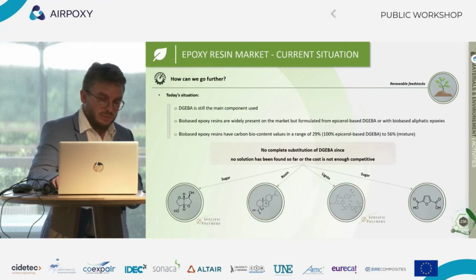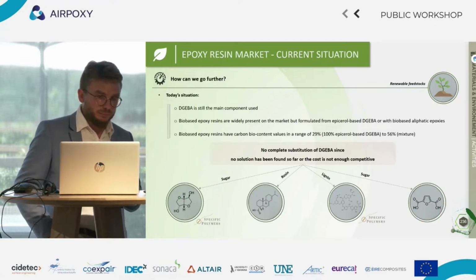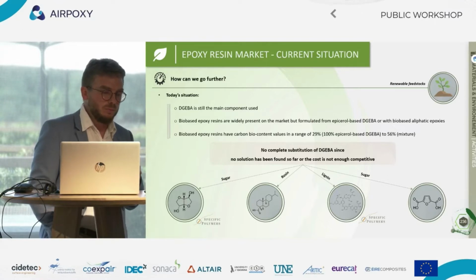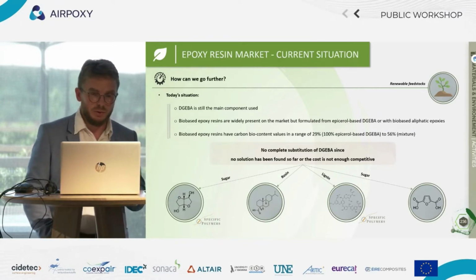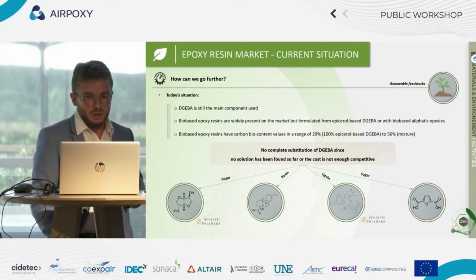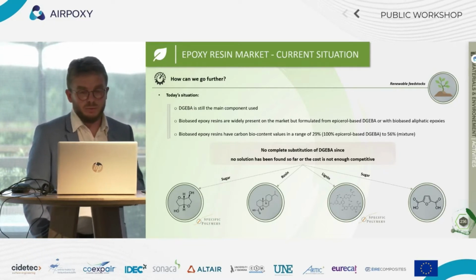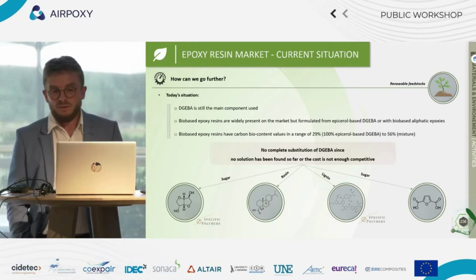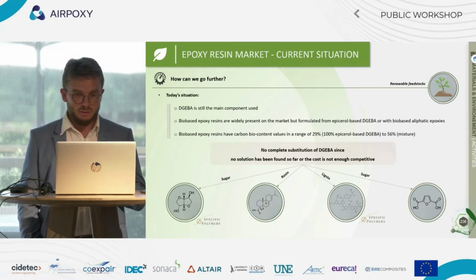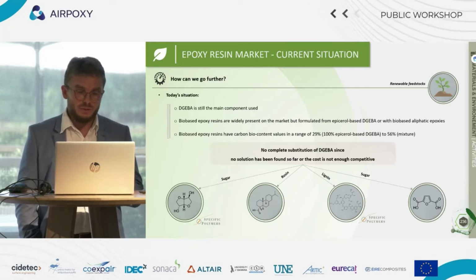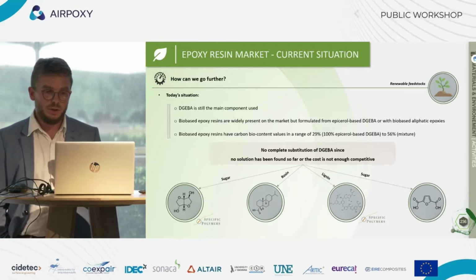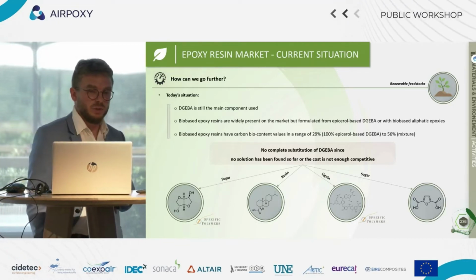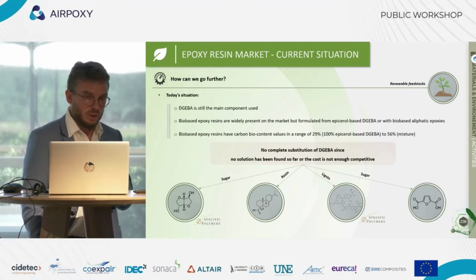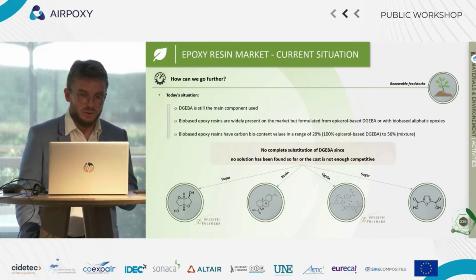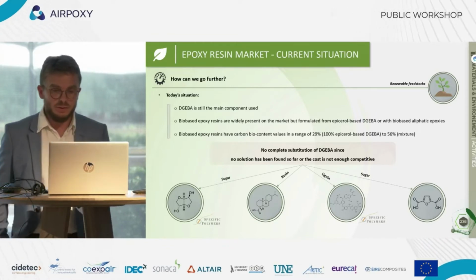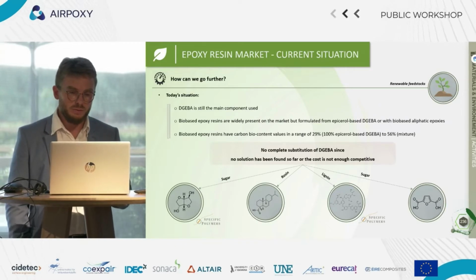So this gives somehow the point where we start, what we want to do. So the problem is DGEBA is still the main component, and we need to find an alternative. Okay, it can be bio-based, but for the moment it's mainly based on Epicerol, and even if it's bio-based, it's still toxic. And with this solution, as was also explained, we can only reach a bio-based content from 29 to 56%, which is not that high at the moment. And it's good to have that already, but we need to go further.